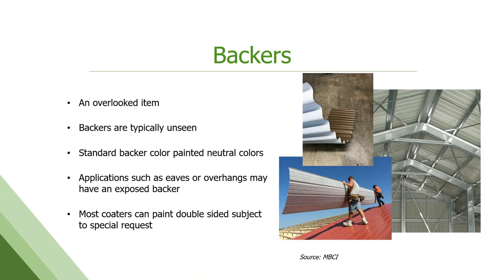Backers, we talked about backers earlier and the need for them is kind of multifold, right? It's a bit overlooked. Most product has kind of a standard off-white or gray backer on it, but you can really do any color. We can coat both sides of the strip with a full coat of paint if you want. Anything's possible, but we try to have a nice consistent backer on there, especially if it's going to be like an eave or an overhang where someone might see it, it's viewable. You want that to look decent and be consistent. But again, it's really to protect the top side finish while in transit and coil form, and then also to give you a boost on corrosion performance.